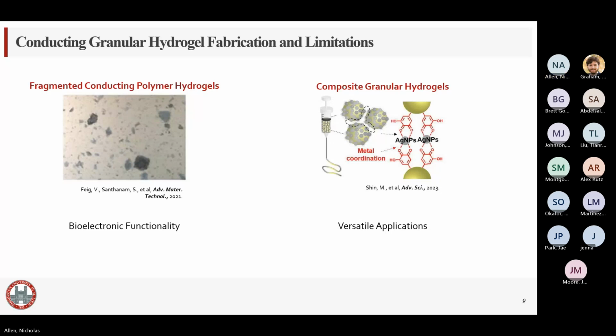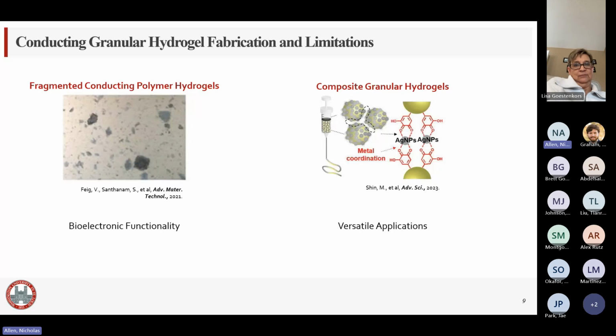So for my PhD project, I decided that my goal was going to be to create a conducting granular hydrogel utilizing pure conducting polymer to achieve that higher conductivity and bioelectronic functionality, but also create a fabrication method that achieved the uniformity seen in the second method, so that I could have the versatility of the end applications as we've seen in non-conducting forms of granular hydrogel.